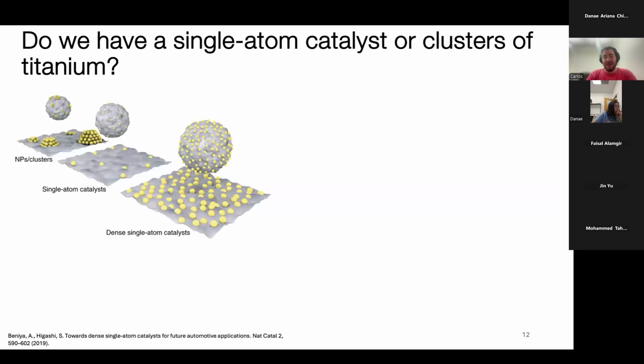The second question that we had is, do we really have a single atom catalyst, or do we have a cluster of titaniums? So what can happen when you're synthesizing this is you might be calling it a single atom catalyst, but you might have the formation of nanoparticles on the surface of the catalyst, which is no longer single atom. And you might be able to achieve a denser single atom catalyst if you have good synthesis procedures. But that's a whole other avenue of research.